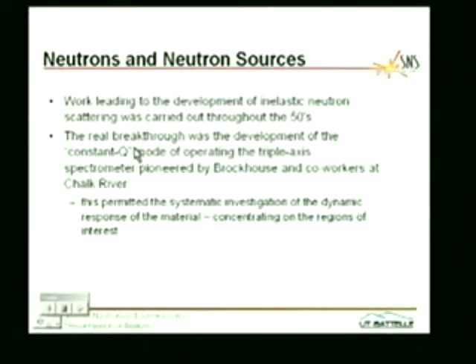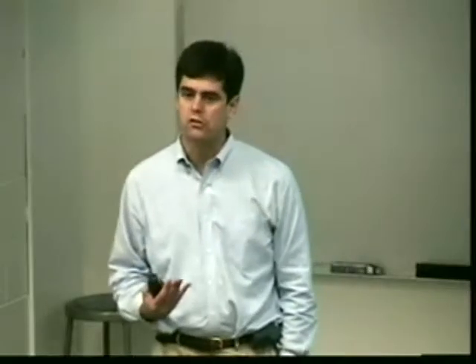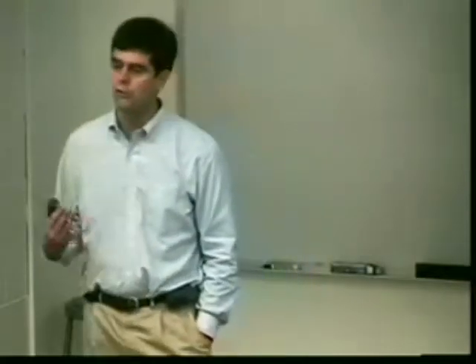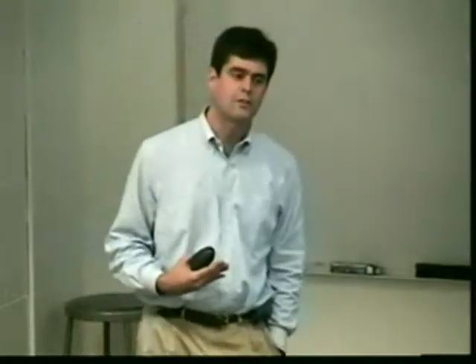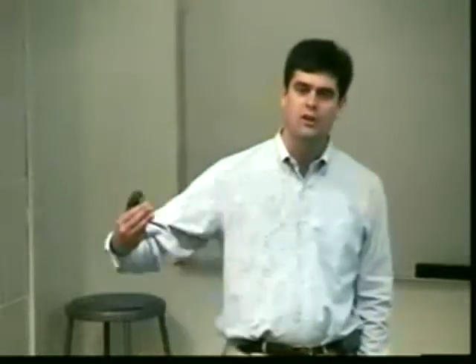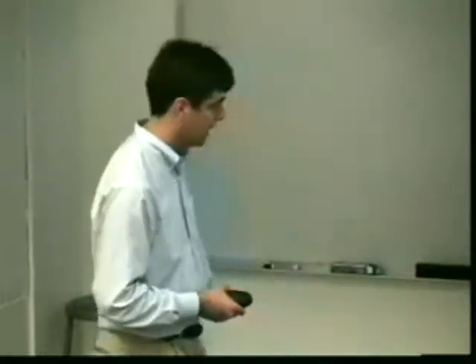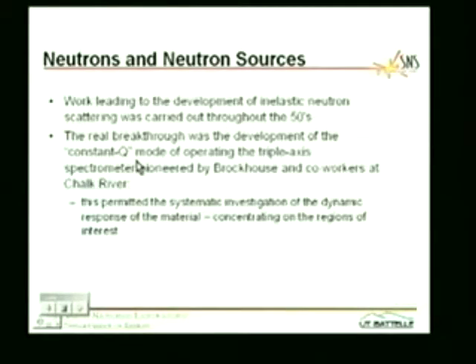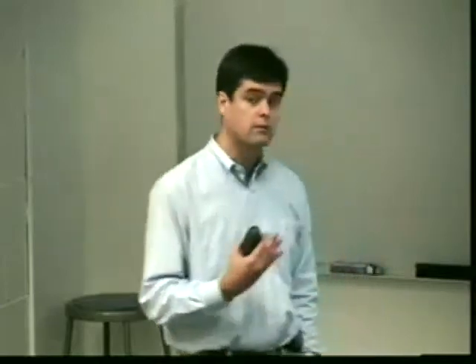The inelastic scattering part took a little longer. The stuff I showed you on diffraction was begun in the 40s with the first generation of research reactors. Inelastic scattering is about 3 orders of magnitude weaker than elastic scattering, so you need to move on to the next generation of research reactors before that's really viable. So that happened throughout the 50s. And a lot of that pioneering work was done at Chalk River by Brockhouse, who shared with Shull the '94 Nobel Prize in Physics. And that really permitted the systematic investigation of dynamic response as well as the statics, i.e. the structure.